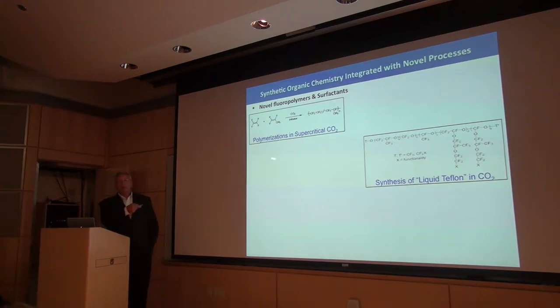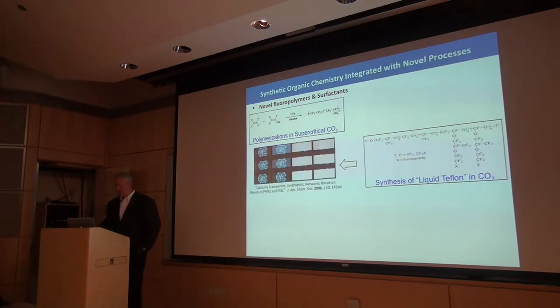These were the two polymers in that first slide. One polymer became the one we did imprint lithography with, and another offshoot is that this polymer is not only lipophobic but also hydrophobic — it's a perfluorinated oil. We had a discovery in the lab that this material was miscible with polyethylene glycol. PEG is very water-soluble and often used as a coating on particles, so it was very surprising that a water-soluble polymer was miscible with something as hydrophobic as a perfluoropolyether. We could make materials at all sorts of molar ratios of these two materials that formed crystal-clear films — they were miscible.